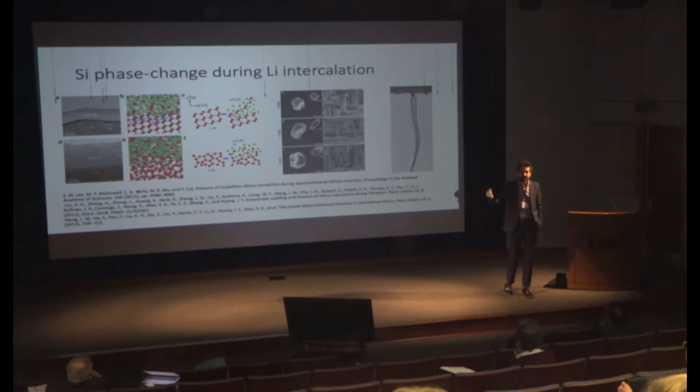Why is that? Because silicon covalent bonds are very strong, and lithium needs a lot of power to disrupt those. They start coming from the side to decouple them and make these intermetallic alloys of silicon-lithium.